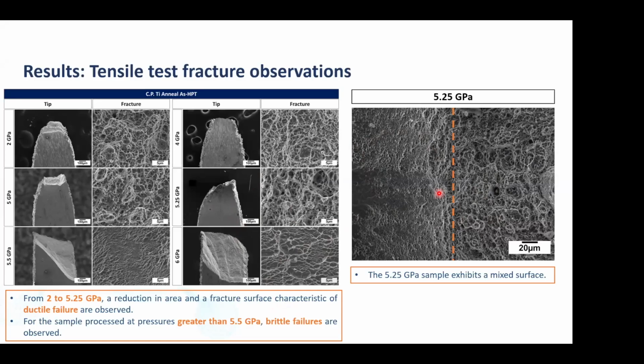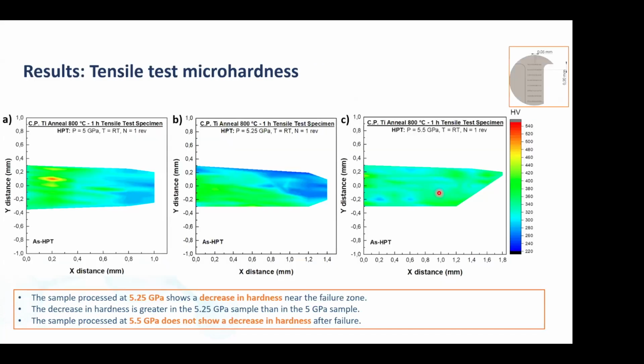How much of the omega phase, or what characteristics does the omega phase have when the pressure and the strain increase, as I showed before. So we did some hardness measurements of the tensile samples, and we see something interesting: at the tip of the samples, for example at 5.25, we see a decrease in hardness after we pull. So we also think that probably the loss of ductility is associated with a dynamic change in the fraction of the omega phase, a reverse transformation at some point driven by the tensile strain, and this is something that we're looking into.